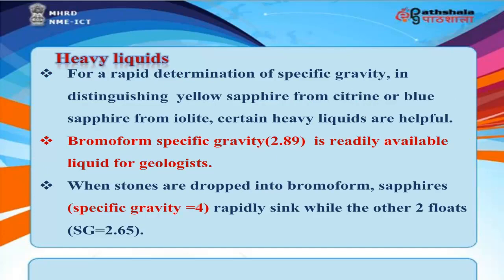Heavy liquids. For a rapid determination of specific gravity, in distinguishing yellow sapphire from citrine or blue sapphire from iolite, certain heavy liquids are helpful. Bromoform, specific gravity 2.89, is a readily available liquid for geologists. When stones are dropped into bromoform, sapphires, specific gravity equal to 4, rapidly sink, while the other two float, specific gravity 2.65.